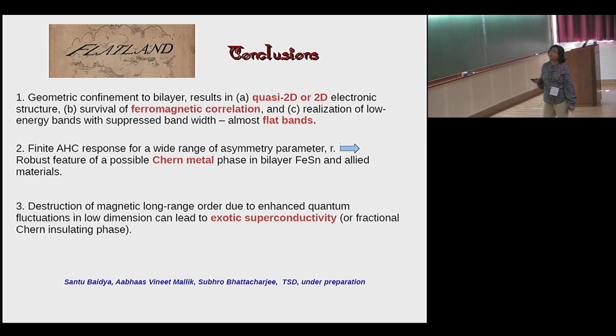So this dimensional confinement to the bilayer of this particular layered intermetallic results in a quasi-2D or 2D electronic structure, the survival of ferromagnetic correlation down to the bilayer limit, and importantly, the realization of low energy bands with a suppressed bandwidth, which is an almost flat band within plus minus 10 meV of the Fermi level, and a finite anomalous Hall response over a wide range of this asymmetry parameter, the asymmetry between these triangles, which is a robust feature of a possible Chern metal. And this magnetic fluctuation can lead to an exotic superconductivity or even the fractional Chern insulating phase, which we are yet to calculate. So this is very much work in progress.